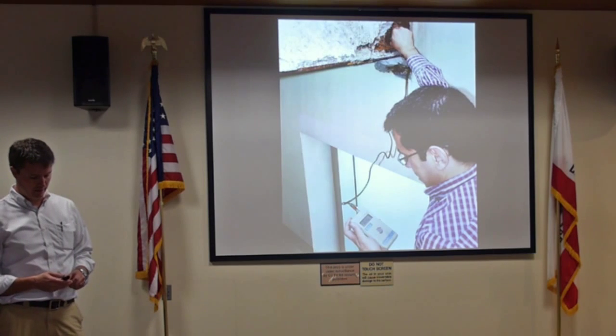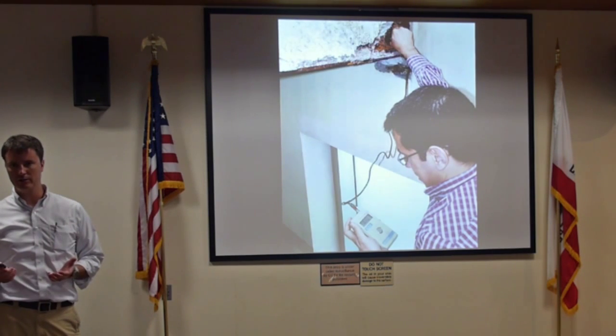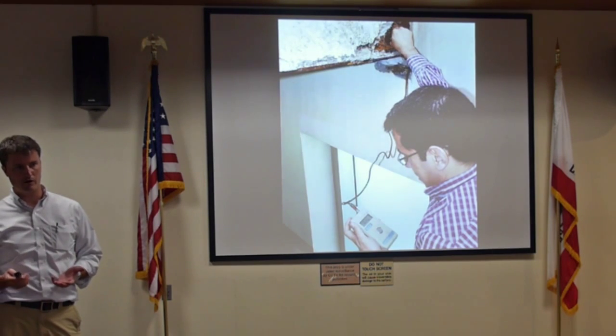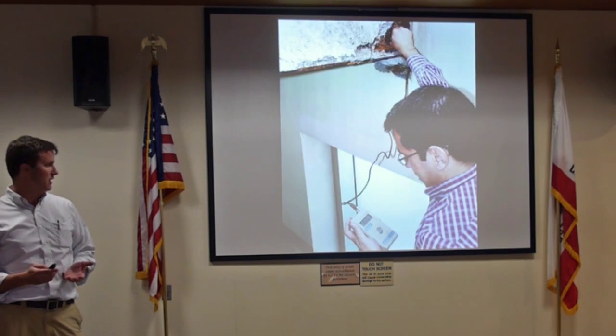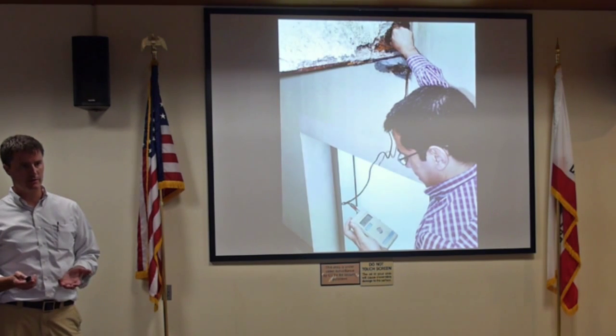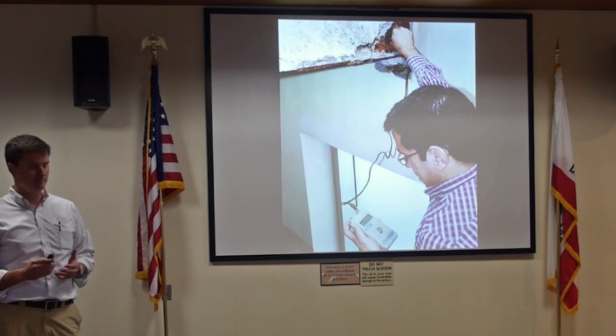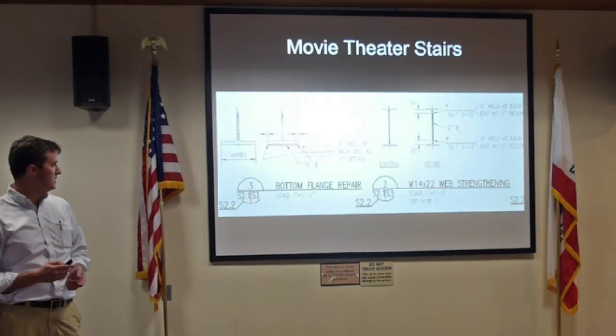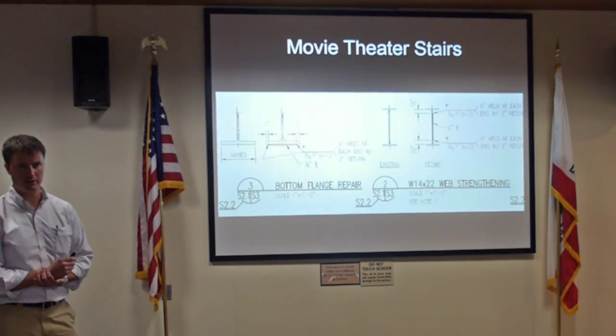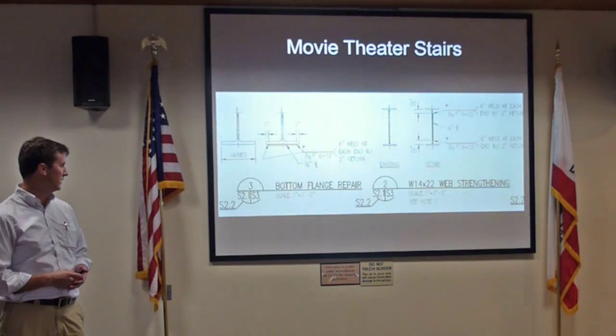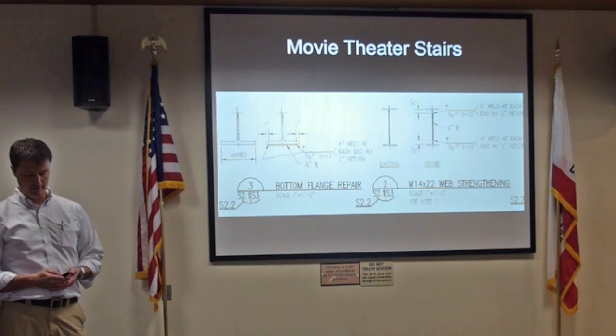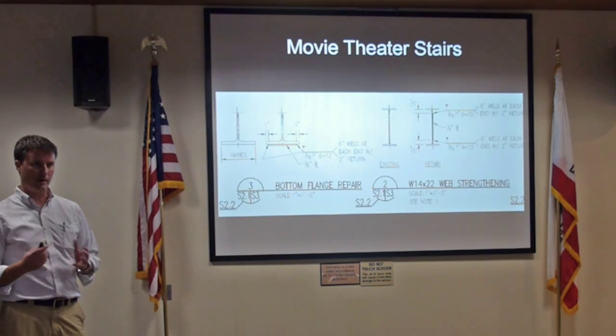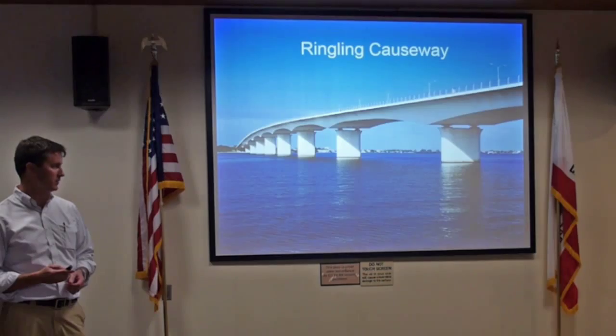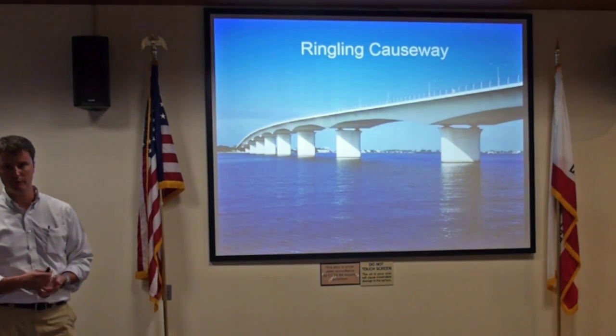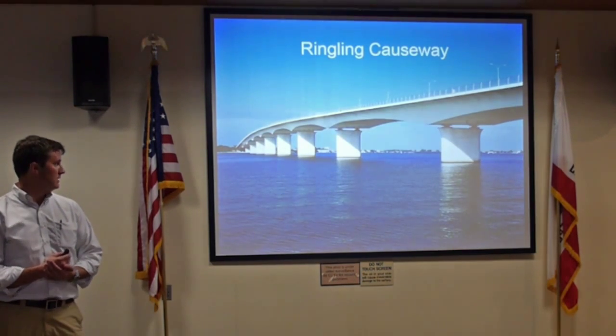So we went through, using an ultrasonic thickness gauge, basically a survey to identify where the areas of section loss are, and in some areas it was as high as 20% section loss, but I'd say by and large it was generally in good condition. We went through the areas where we identified section loss, strengthened with welded steel plates, and then ultimately came back with proper cementitious fireproofing, which they installed. Great, which we just saw yesterday.